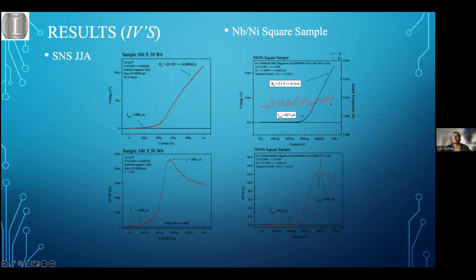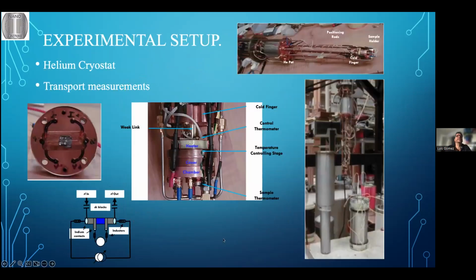Now this sample has much more resistance. As I increase the current, the sample starts dissipating, so my thermometer starts showing heating in the sample. The sample thermometer, if I show you, was over here. I have a control thermometer, this one over here, which I use to control my heater. But there is another thermometer closer to the sample, farther away from the heater source. This one tells me the temperature of the sample itself. So this thermometer is affected by the dissipation of the sample, whatever is happening in the sample.